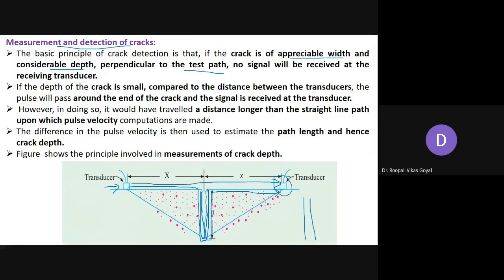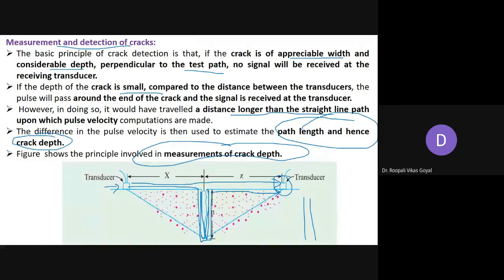So if you are getting at some point a longer path length as compared to the other one, then you can say that at some places the crack would be there. So if such kind of cracks are there, the distance traveled would not be a straight line, but a longer path length. From this longer path length, you can estimate the crack depth also. So this measurement of crack depth is also a very important application of this pulse velocity. Just by having more path length, you can estimate that there is some crack inside.